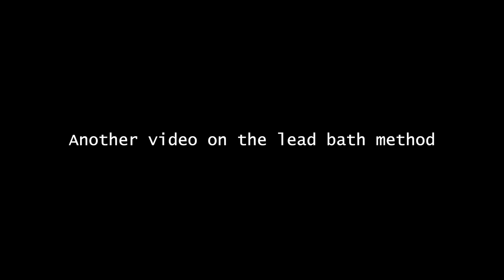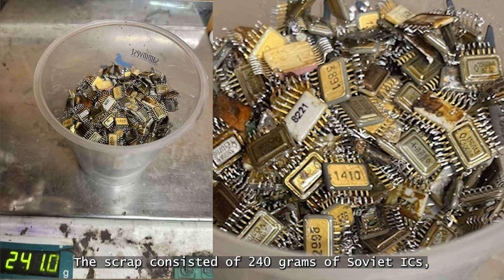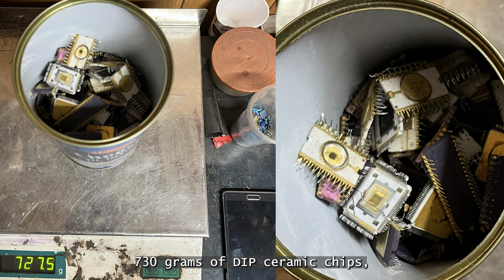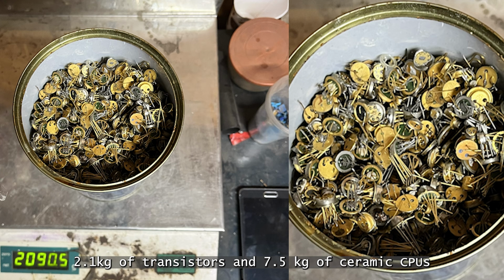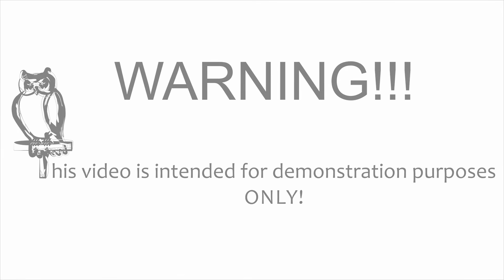Hello. Another video on the lead bath method. This time though, we started with 10.5 kilograms of scrap. The scrap consisted of 240 grams of Soviet ICs, 730 grams of DIP ceramic chips, 2.1 kilograms of transistors, and 7.5 kilograms of ceramic CPUs.